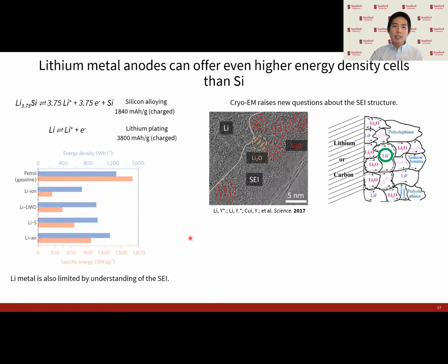So the first demonstration of cryo-EM by our group allowed us to look at the lithium SEI, which actually looks fairly similar to this original model, this classic model of the SEI that was proposed back in the 90s. But it also introduces some new questions. Specifically, the lithium oxides and the lithium carbonates within the SEI do match this model, along with the organic materials that are presumably the organic carbonates and other polyolefins within the SEI.